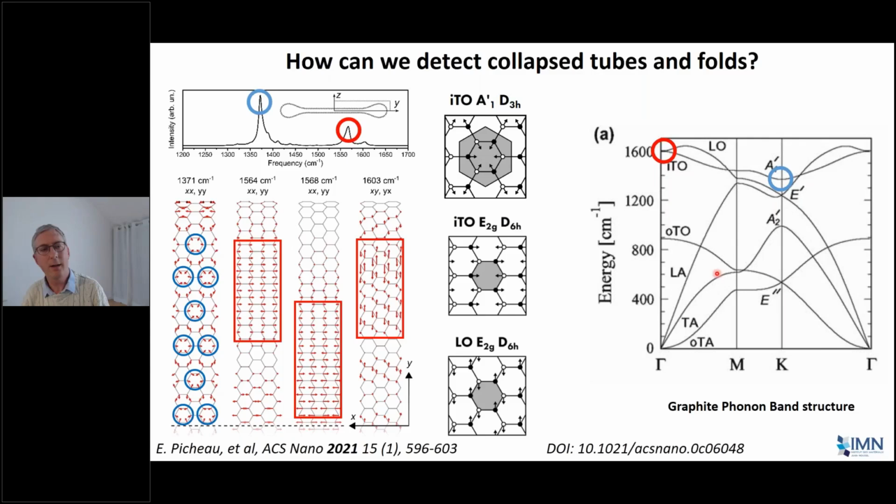So what's happening in this case is that the edge is breaking the symmetry. So your perfect graphene sheet or your nice round nanotube won't have this mode because it's too symmetric. But by putting an edge in, you break the symmetry, and this mode now folds onto the gamma point, and so you can see it. So you're not actually damaging the nanotube in the sense of putting in point defects. You're only damaging it by breaking the symmetry, but that's enough.